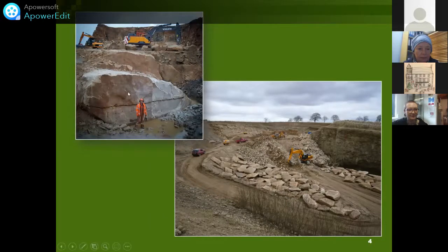So just looking at this, you can see here we've drilled and used black powder. So we've drilled about 40 holes along here, and that block is about 2 meters high. It's about 2 to 3 meters deep, and it's about 7 or 8 meters long. That block, when it came out, would have weighed in excess of about 120 tons. And then that's split up into sort of usable 10-ton-ish blocks to go onto primary sawing.